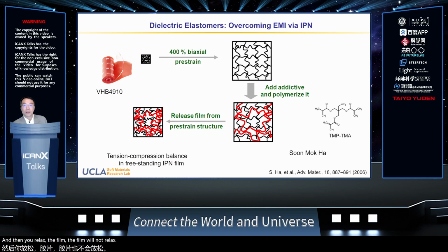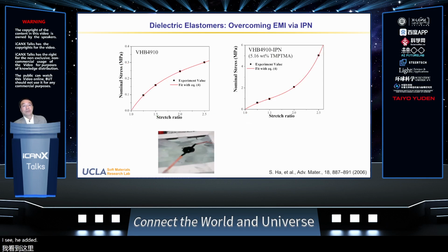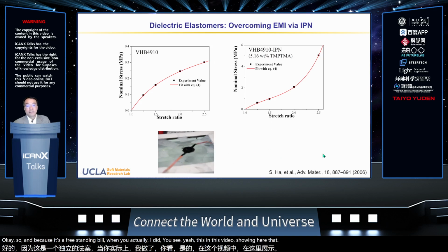The film will not relax to the original shape because the additive forms its own network to support the structure. So in the finished freestanding film, you have the original VHB network in tension, while the additive network is in compression. For this kind of IPN film, the right chart shows the stress strain behavior, where the stress strain plateau is narrowed so that above a stretch ratio of 2, you see a rapid rise of the stress. Because it's a freestanding film, when you actuate it, as you see in this video, the surrounding area is not stretched, so the film just shows buckling.